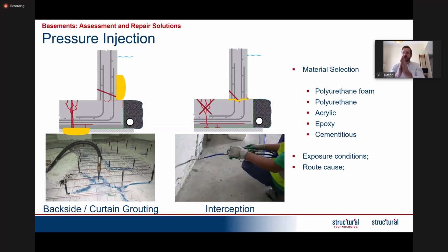So for example, if the crack is due to movement in the wall and you inject in a rigid material, for example an epoxy, then you're preventing that movement which is required. So then probably you would induce another crack next to the one that you just sealed. So in most cases, if you have through and through cracks in walls, you would be injecting an elastomeric sealant which has some kind of flexibility.